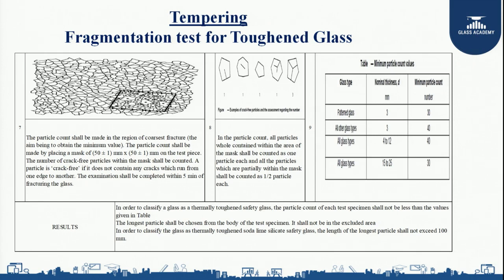After breakage we need to start counting. The number of crack-free particles within the mask shall be counted. A particle is said to be crack-free if it does not contain any cracks which run from one edge to another. The examination shall be completed within 5 minutes of fracturing the glass.